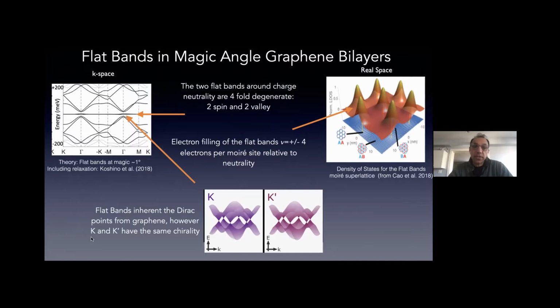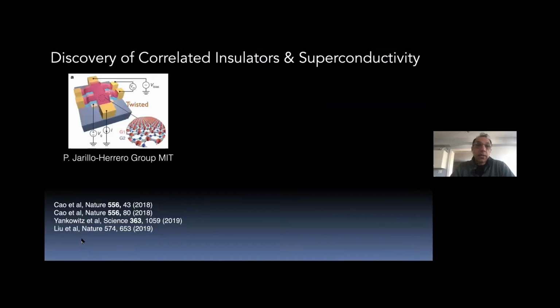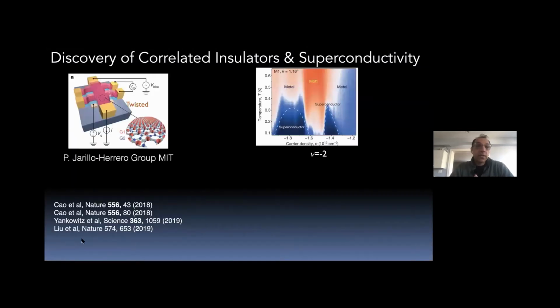The other special property it has is that it inherits the topological, if you wish, the Berry phase that comes from graphene Dirac cones. And if you zoom in on those flat bands, they actually have Dirac points. And this gives rise to the topological phases that you heard from Dimitri about, when we start to cause perturbation on these Dirac points, either via single particle physics, or, as I will show you, through interactions, which is very novel.